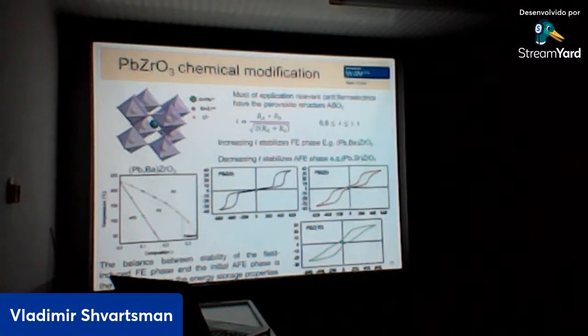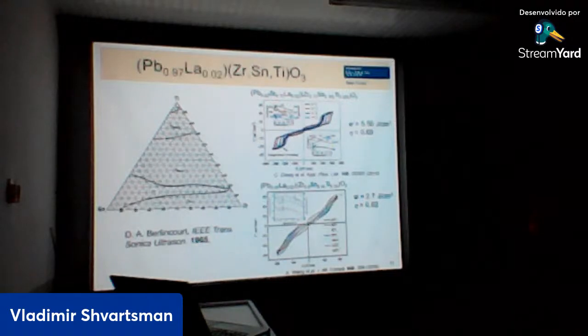Therefore people play with chemistry, with doping of, for example, lead zirconate, to find the optimal compositions. So here is one example. One can add tin, and tin will strongly reduce this critical field. And you see, for example, here quite a complex material. We have lead and lanthanum on the A side, zirconium, titanium, and tin on the B side. But we can find a composition with pretty good parameters.